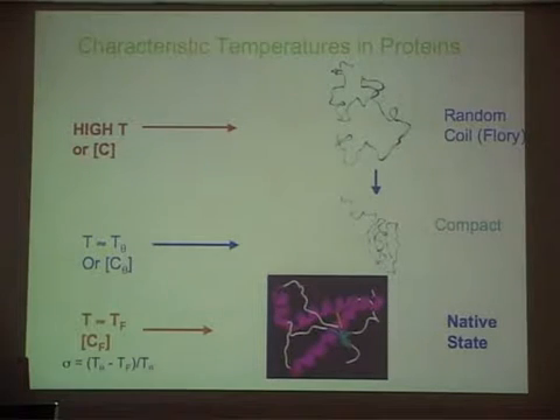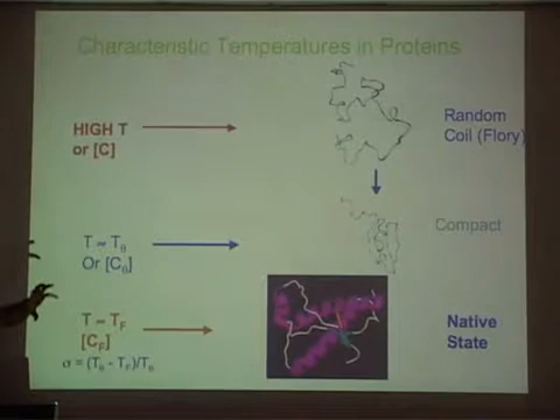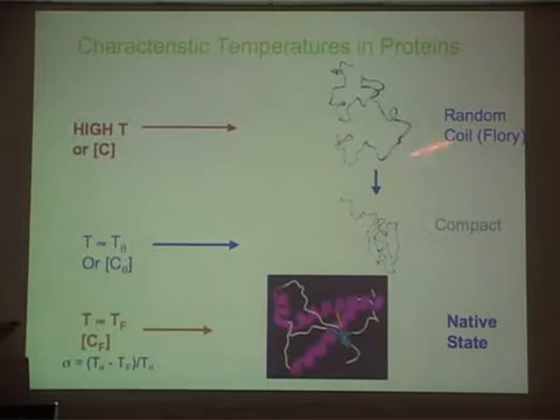And before I do that, let's think about what kind of phases, if you wish, you would get in this protein folding problem. Long ago, Flory told us, and this long ago is 1948, that if I take a polymer, and this is something that Giant briefly described, and then you make the solvent good for this polymer, which means the interaction between the monomers of the polymer is more favorable to the solvent than interactions within the monomer, and therefore the polymer would actually swell, and that's what he understood, and he described a theory for how to predict the dimensions of such a polymer in a good solvent.